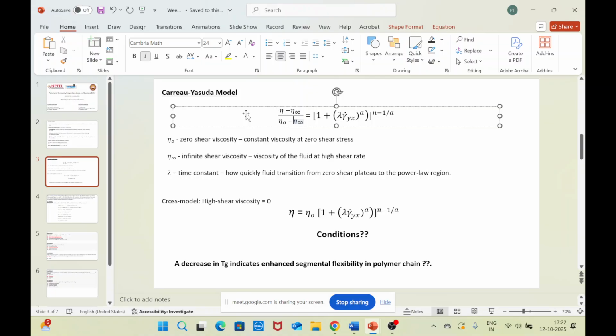We discussed the zero shear viscosity, the infinite shear viscosity, and the time constant. What is the significance of the time constant? Based on this model, we introduced a constraint by stating that eta infinity equals 0. We reduce the model to a simpler form: eta equals eta naught times (1 plus (lambda times strain rate) to the power a) to the power (n minus 1) by a. So this becomes a 3 parameter model. Here we have imposed the constraint that the infinite shear viscosity, or the high shear viscosity, should be equal to 0.